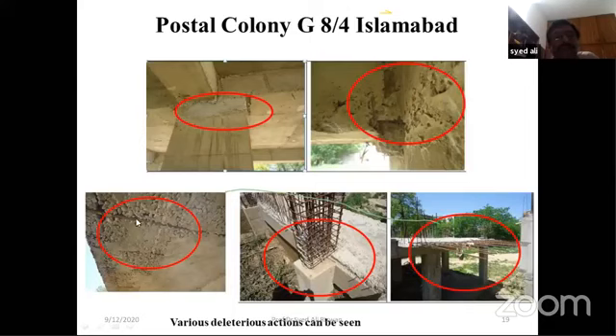And you can see this honeycombing. And as a material expert, you can see that the mix was not okay, its consolidation was not okay. The paste content was less, so that you will have more aggregate, and aggregate size was also quite high. The higher size of aggregates also usually results in lower strength of concrete.